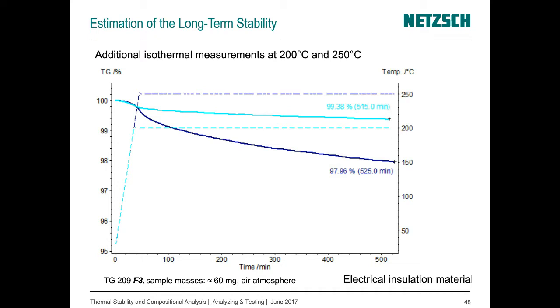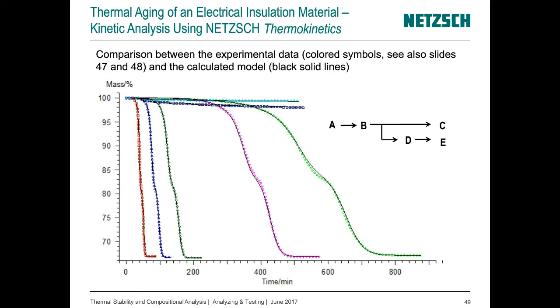It's an isothermal measurement at 200 degrees C, the light blue curve, and at 250 degrees C, the dark blue curve. If we look at the time scale, we have more than 500 minutes, and within this time we have in the light blue case about 0.6 to 0.7% mass loss, and in the dark blue case about 2%. The task for the kinetic evaluation is now to find a model which describes all these experimental curves as well as possible.